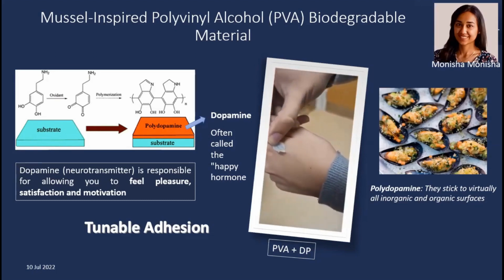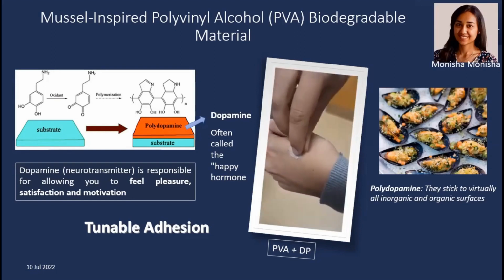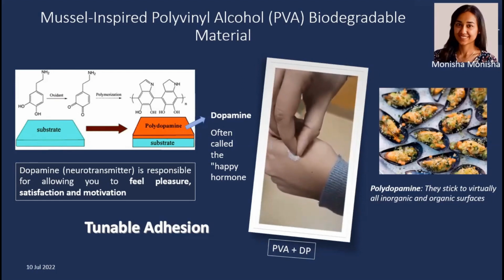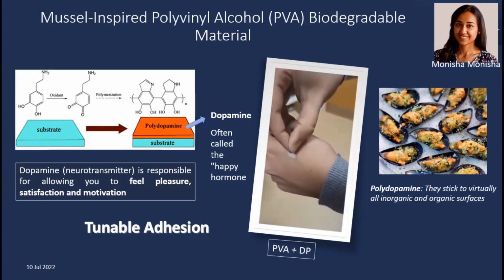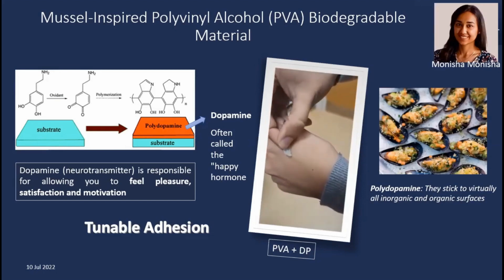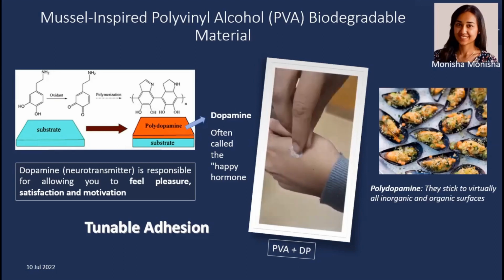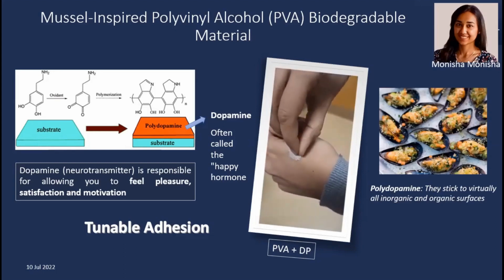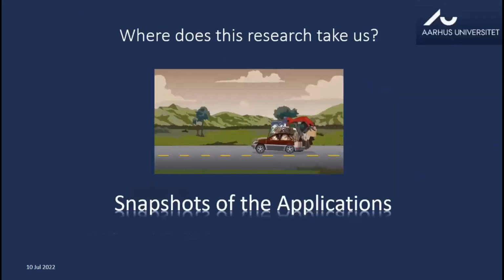The next step that she is doing now is she wants to create a sticky electronic surface for an application that we have. We have funding for that. And now she's trying to convert this insulator. This is a completely insulating material. So this is the substrate. And now we are infusing electronic properties into it to make it conducting. So we are again trying to play with the polymer chain here so that we are changing its electronic properties, so that we can get a transition from an insulator to a conducting material. The vision here is to have the same material substrate and the same material chain, with electronic material printed on top of it. Because then you don't have the interface issues that you face with multi-material printing. If you have two different materials, you will face a lot of interfacial problems when you want to print on them. But if they all belong to the same polymer chain, that makes your life much easier. And that's the vision of this. So we have been doing a lot of material studies, right?